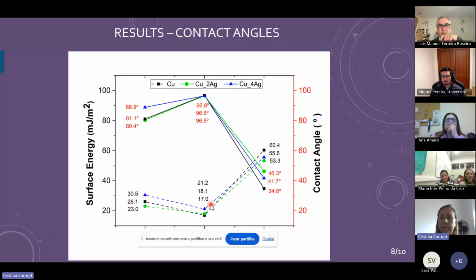About wettability, the presence of silver promotes a decrease in surface energy and a higher contact angle. After 1 year of natural aging, the surface energy reduces, and we have an increase in the contact angle, as expected because of the process of oxidation. The oxides are more stable. On the other hand, with retreatment, we have a decrease in contact angle and consequently an increase in surface energy.